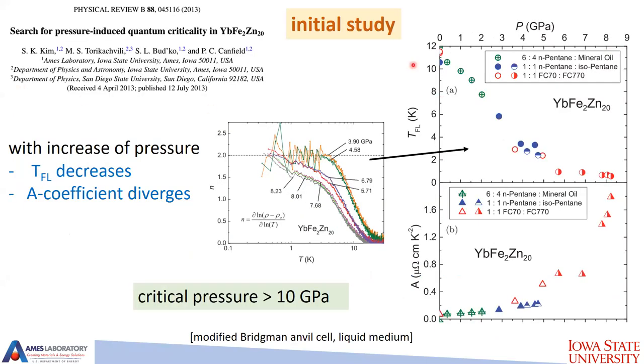So we started with a modified Bridgman anvil cell. We were watching two things. We were measuring resistance, or resistivity if you wish. We were watching at which point we have T-squared behavior, and that's the Fermi liquid temperature. And we were watching the A coefficient when we're in the Fermi liquid. Everything was going just fine. The Fermi liquid temperature goes down as per the Doniach phase diagram, and the A coefficient in front of T squared goes up, again as you would expect for a Doniach phase diagram.